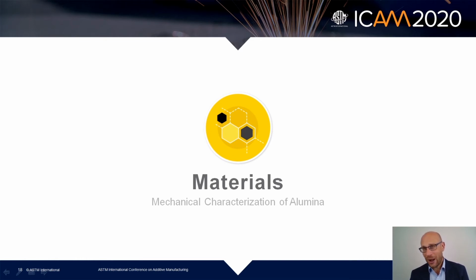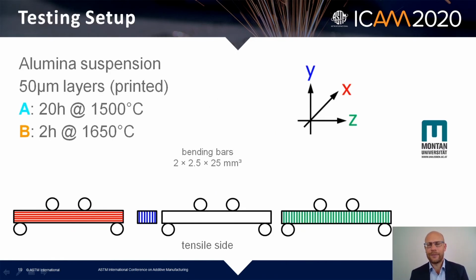Now let me talk a little bit about the mechanical characterization of alumina. Why is it important? How to characterize it? I think we have done a very nice study together with the Montanuniversität in Leoben, where we did very clear research on how to test and what to test. First of all, we had two different sintering temperatures and holding times. Material A was held for 20 hours at 1500 degrees, and material B was held for 2 hours at 1650 degrees C.